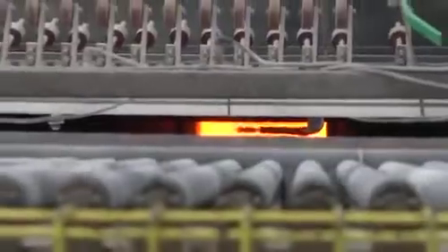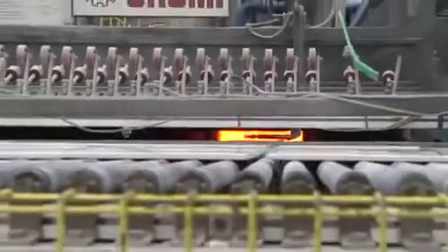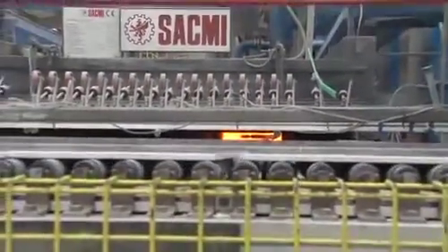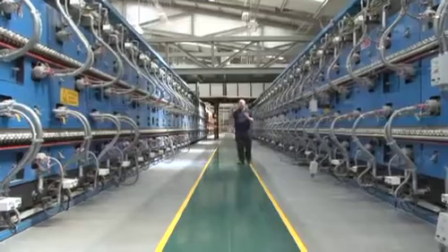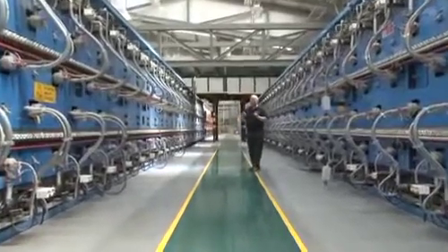As it enters the main firing zone and exits the main firing zone, it goes through a rapid cooling process, and then the tile has to be gradually cooled as it exits the kiln so that there's no thermal shock which would result in failure.